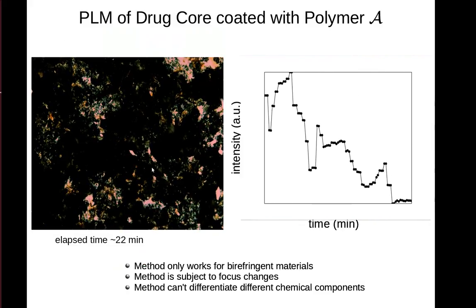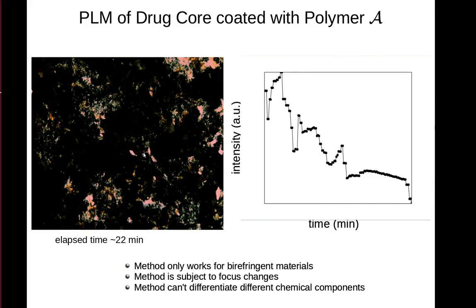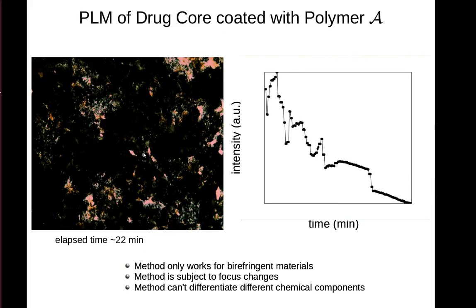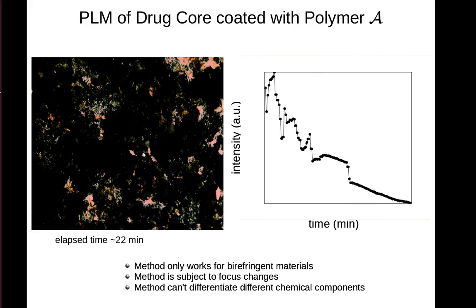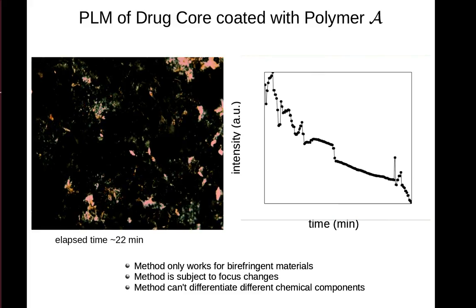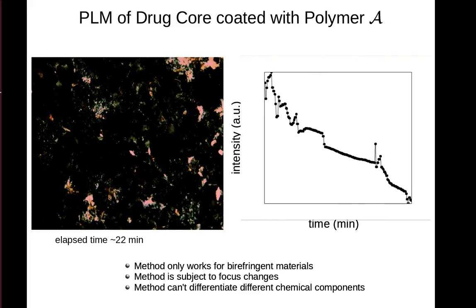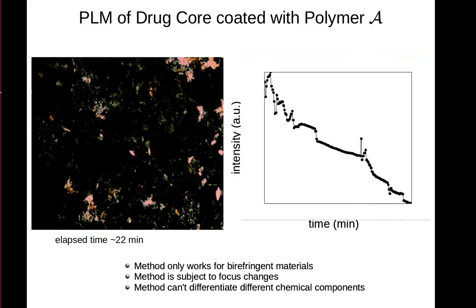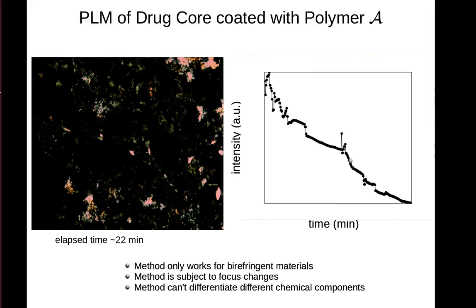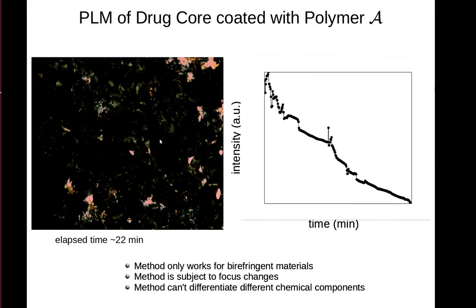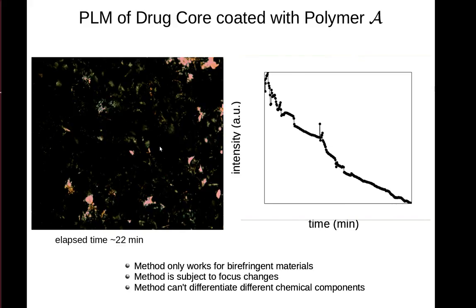Here we see the beginning of this experiment. The water is penetrating through the polymer. At some point, it dissolves the polymer, and we start to see the API float about. If we look at the intensity on the right, we see the intensity decrease right from the beginning, and there's a bit of a knee where we've seen from the image that it was very likely that the polymer dissolved, allowing the API to float about.